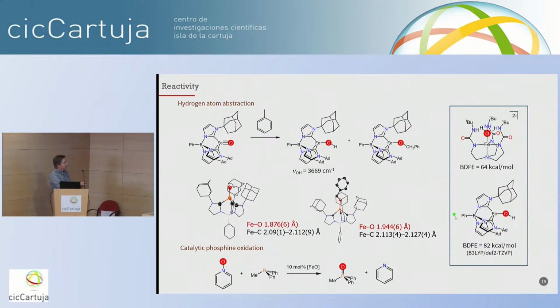We also computed the bond energy. So the OH bond strength that's formed, we compute to be around 80 kcals per mole. It's much stronger than the bond formed from, for example, the Borovik oxo complex, which is around 64. And I think this demonstrates again how the hydrogen bonding network here really attenuates the reactivity of the oxo ligand here. So it decreases the OH bond strength for the hydroxide that would be formed.